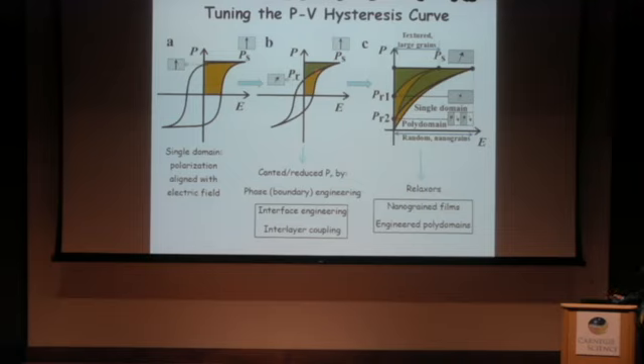But there's another way, I think it's well known in the field, that you can utilize an interface layer, so-called space charge layer or dead layer, to tune your ferroelectric PV loop from a square-shaped loop to a more slim loop. That's well known in the field. So here, I would propose a way of introducing inhomogeneity in the thin film. I'm not having a single-phase, single-domain film anymore. Instead, I can have relaxor, polar nano regions, or we can engineer the grain in polycrystalline film, or the domain structure in epitaxial film.